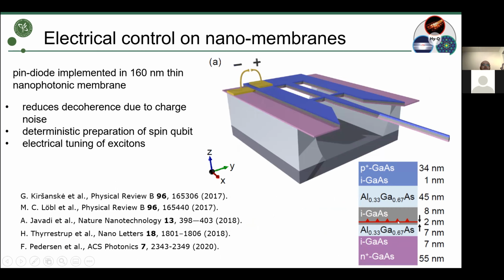And that is very beneficial for the quantum dot emission because it reduces all the noise that is coming from, for example, random charges that are around the quantum dot. But also very important, it allows for the electrical tuning of the excitonic transition, so for this electron-hole pair. So let's say you have a quantum dot that emits at 930 nanometers, you want to bring it to a different wavelength, then you apply a field and you tune this emitter to a different wavelength. So that gives you another knob to control your quantum dot.